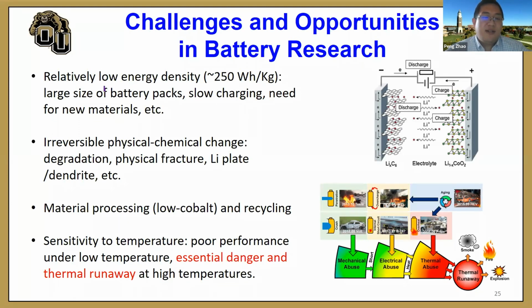The first one is that the lithium-ion battery has a relatively low energy density. The typical energy density is about 250 watt-hour per kilogram, which is about 2 orders of magnitude lower compared with the value of gasoline and diesel, which is about 45 megajoules per kilogram. That leads to the necessity of large battery packs in the vehicles, and that aggravates the slow charging problem. That also drives the need for the exploration of new materials.